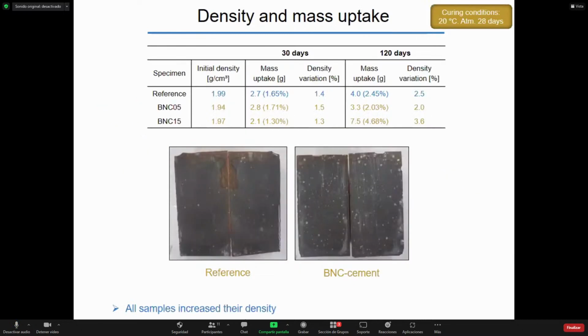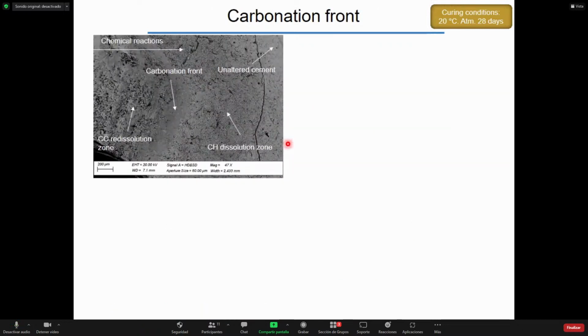After carbonation of the sample cured at 20 degrees Celsius, we saw that there was major degradation at the top of the samples, but they were not completely carbonated as we expected. We also saw that density increased after 30 and 120 days of carbonation due to the precipitation of calcium carbonates in pores. To generate interfaces in cement.